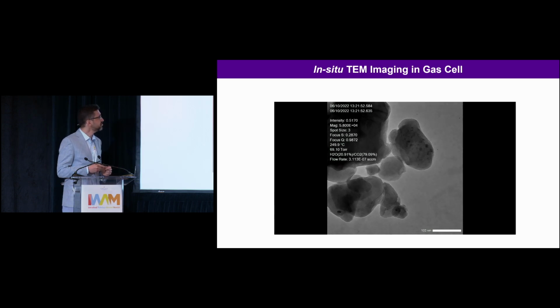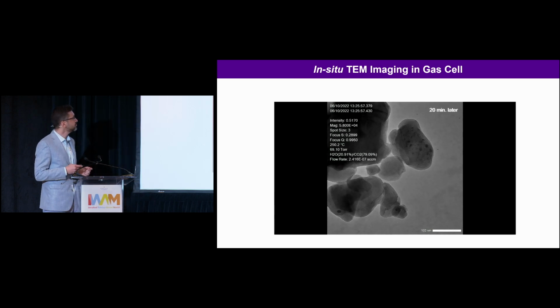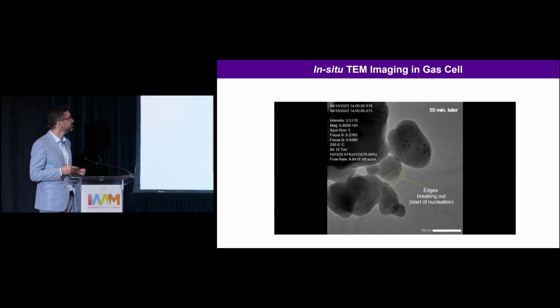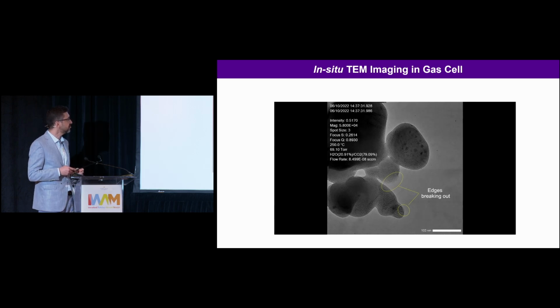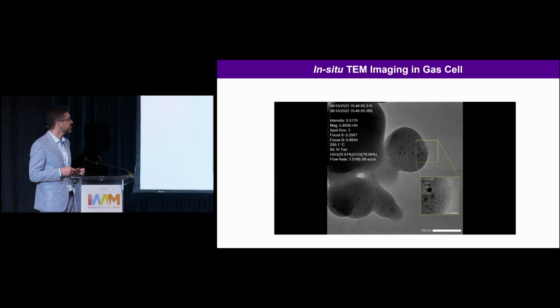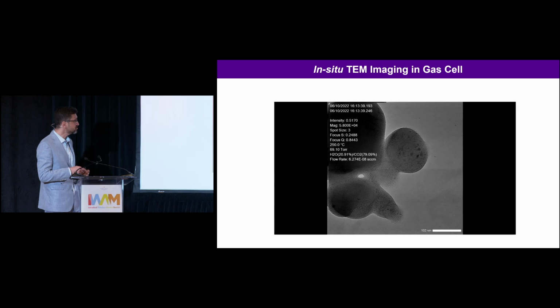So after around 20 minutes, we are able to see some round shape going around, and then after around 1 hour, there's an edge breaking out and start of nucleation, and then growth on these edges. And after around 2 hours, we see small, nano-size particles forming in the microstructure. And we suspect that it is an amorphous magnesium carbonate because there is no clear pattern in